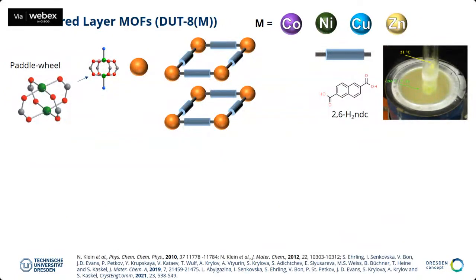So, what is this magic material DUT-8? It's a very simple architecture. It consists of a paddle wheel. We found this out by single crystal X-ray diffraction measurements. This is a binuclear complex, which is often called a paddle wheel in the MOF field. These are connected to four carboxylates, and the carboxylate in this case is a naphthalene dicarboxylate.